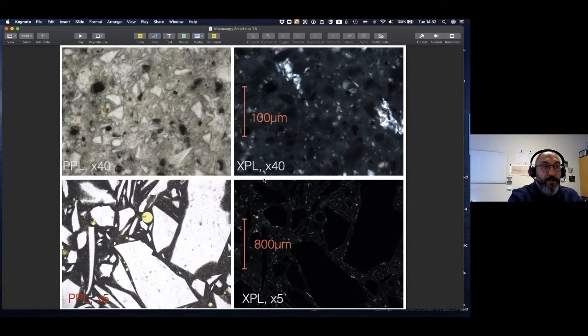You can observe not only ordinary Portland cement, of course, but also other binders such as slag. Slag is quite popular in the Netherlands. We use quite a bit of blast furnace slag cement. On the top, we see the blast furnace slag cement paste. On the left-hand side, you see the plain polarized light. Natural colors, all the grains are visible, everything's fine. If I go to cross-polarized light, you remember if it's super dark, it would tell me that I have amorphous grains, and all these white grains you see on the left side, you see them quite dark on the right-hand side because they are all amorphous and they are showing isotropic features, which means dark.